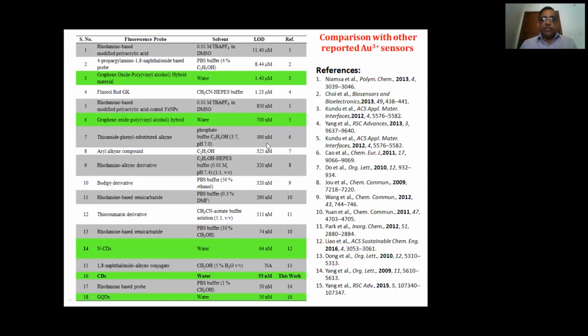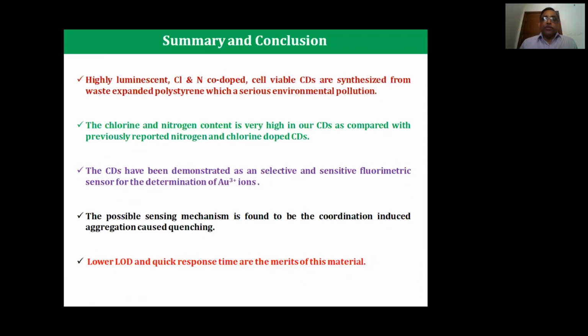As we said, the best literature reported is still around 50 nanomolar. This work gives 53 nanomolar. When you compare to other reports, they're all at larger LODs, so we could really see the enhanced limit of detection for the gold ion from this material.